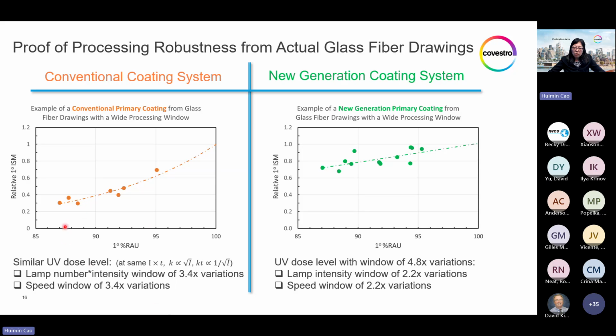The conventional coating was set with 7 different conditions, all tuned to similar UV dose, with lamp number combined with intensity variations up to 3.4 times, and accordingly, speed window also 3.4 times variation. And notice the resulting conversion ranges from 87 to 95, even at these similar dose levels. Without more detailed discussion here, I listed some simple kinetic explanation of why, under the same dose, the change of intensity does cause cure degree differences.